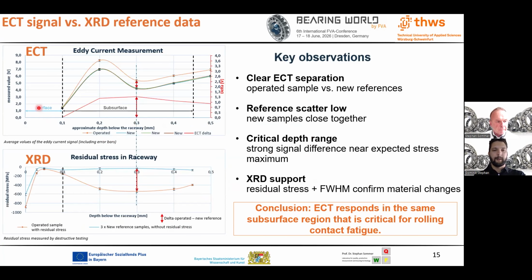This slide summarizes the comparison between the eddy current signal and the X-ray residual stress data. On the top, we see the ECT response. On the bottom, we see the residual stress profile measured by X-ray. Both methods show the most relevant changes in the subsurface region. The ECT signal difference occurs near the same depth range around 0.3 millimeters, where the X-ray data shows a change in residual stress. This does not mean that eddy current directly measures residual stress, but shows that eddy current responds to the material state in the fatigue-relevant subsurface region.